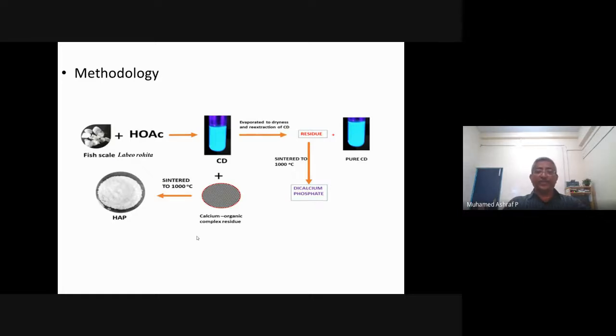The fish scale we have treated with acetic acid, and then we get a carbon dot plus a calcium organic complex residue. That residue we have sintered to 1000 degrees centigrade, and then we get a pure white hydroxyapatite. If you extract hydroxyapatite directly from the scale, the color is a little off-white, but here what you get is very pure white hydroxyapatite, and it is better than our synthetic additives.